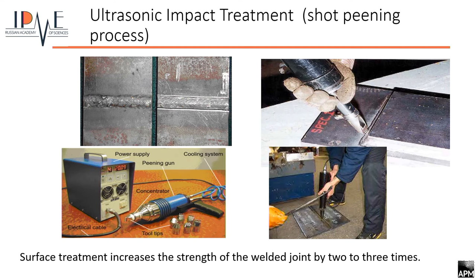Treatment surface very small. It is the steps of treatment. With such a small device, the power of this device is only, for example, 400 watts. And after treatment of such a small surface, we increase, for example, the strength of the welded joint by two to three times. And it is a very interesting result.